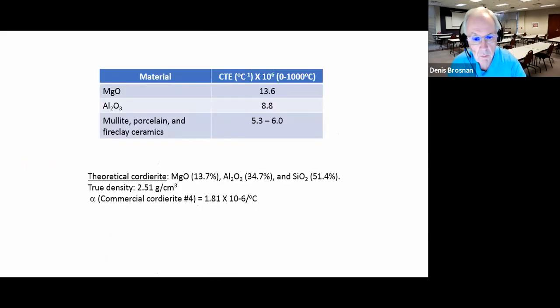Now, the reason that we like to talk about cordierite is it has a very low thermal expansion coefficient. The thermal expansion coefficient is the slope of the thermal expansion line, thermal expansion in percent or unit dimension per degree of temperature. Per degree Celsius, the thermal expansion coefficient of cordierite is pretty darn low. We use the Greek letter lowercase alpha to denote it, and you can see that it can be down around 1.8 times 10 to the minus 6 per degree Celsius. It's inches per inch per degree Celsius, or centimeters per centimeter per degree Celsius.